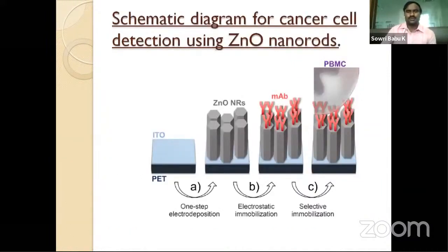Okay. So this is what we have done for detecting cancer cells by using vertically grown zinc oxide nanorods by using electrodeposition. So we have the polyethylene terephthalate substrate, okay, over which indium tin oxide is coated. We have different types, like FTO, a fluorine doped tin oxide, is also there. Anything we can use. So PET ITO, over which we have grown zinc oxide nanorods by using the electrodeposition technique.